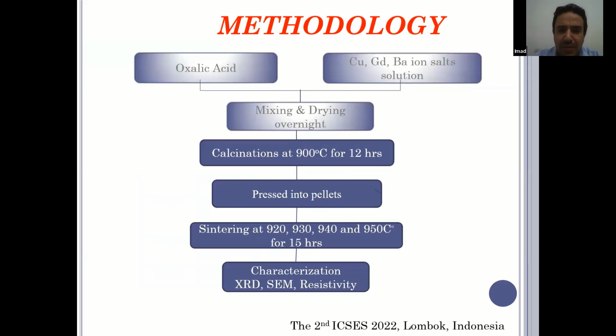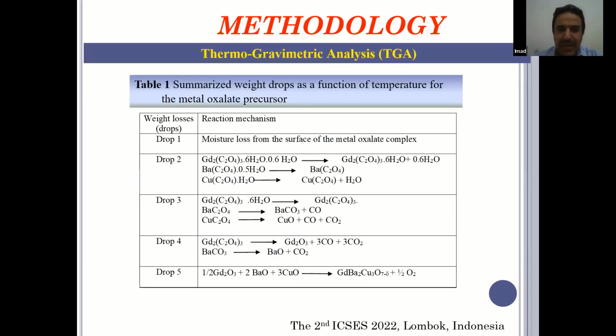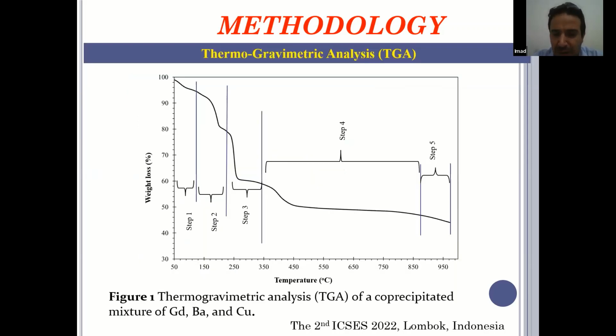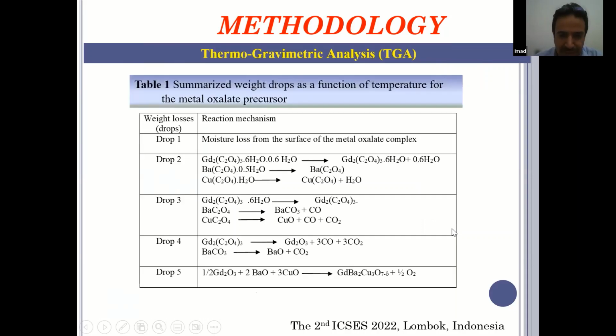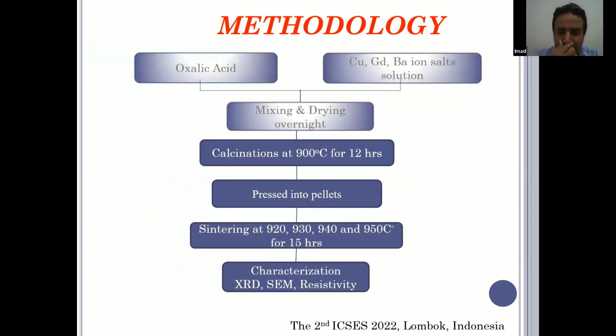After that, we continue with the calcination, and based on the TGA thermogram, we found that the best temperature for calcination and sintering is above 900 degrees centigrade. So we do a calcination at 900 degrees centigrade for 12 hours, and then we cool down the system. We grind the material for 5 minutes. Then we press it into pellet form, and then subject it to heat treatment at 900, 920, 930, 940,